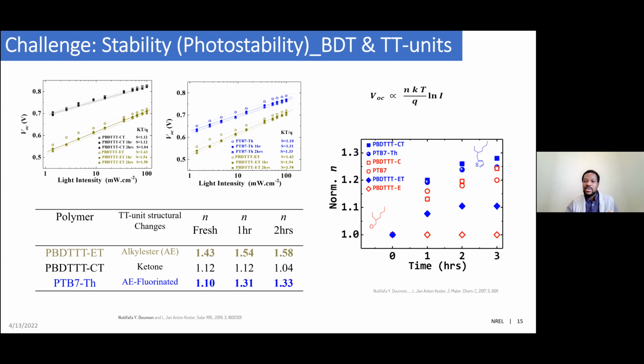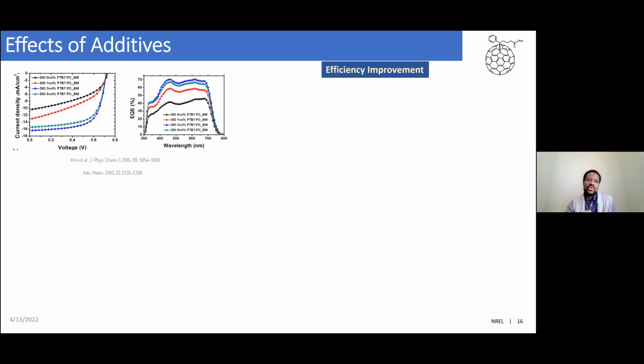We try to do the same thing also for the blue and the red polymer. And here we can clearly see that with each counterpart, the red polymer retains its ideality factor nicely over time, though it increased, but the blue polymer increases faster than the red polymer. So this leads us to the next technique, which is the additives.